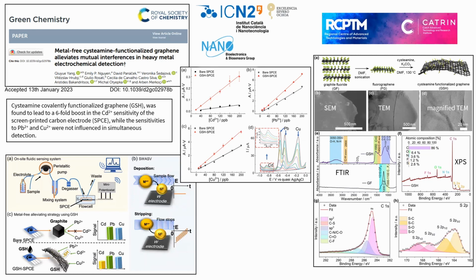So recently, and this is also a few days ago, we also showed how we can improve these metal detections using electrochemical stripping, thanks to collaboration with our partner in the Czech Republic, who supplied us with this metal-binding system. We are able to use this electrochemical system to detect the heavy metals incorporated on top of the electrode. So this system was able to enhance the response to cadmium and make it possible to reveal it even in the presence of high concentrations of copper and lead, which is a big problem for heavy metal detection. Showing, for example, here that with this system-modified graphene surface, we have a higher sensitivity in comparison to the bare electrode that does not contain this functional group.